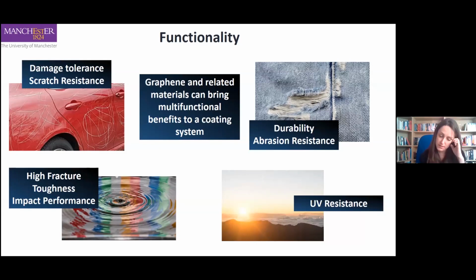All these properties have an effect on a coating system. So if you have graphene incorporated into a nanocomposite coating system, it can show enhanced toughness. It's stronger. It can help with issues such as abrasion, wear and scratch damage. Because the surface of the coating is tougher, it has better resistance to impact. And this is relevant to coatings over lots of different industries. Anything that's subjected to extreme external forces or moving parts.